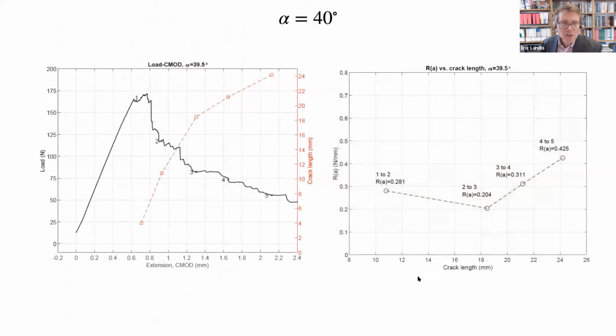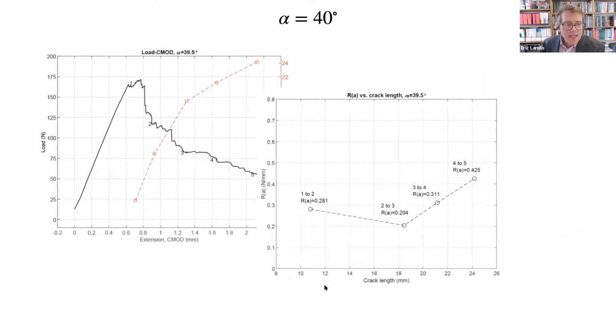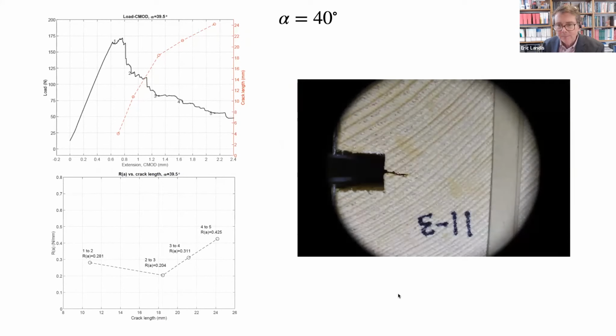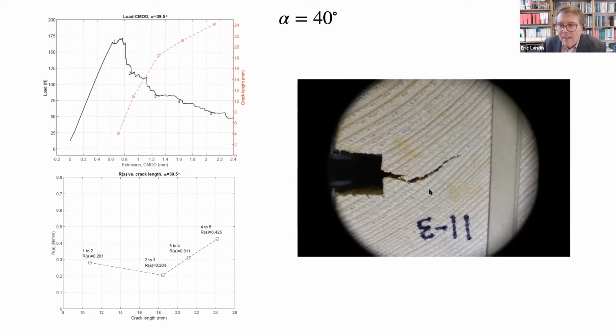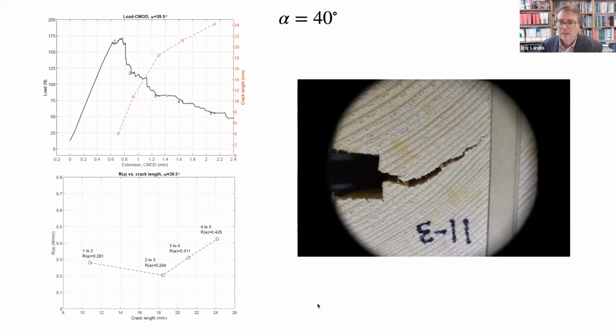Now, an interesting thing starts to happen just a few degrees more. Again, we see some instabilities, but otherwise stable crack growth. But now in this case, looking at the cracks, we see the crack wanting to follow that early wood path, but the angle is steep enough that we start to cross over the late wood, which means we've got to break through what would seemingly be a stronger section of the material.